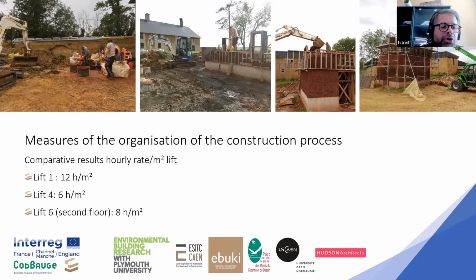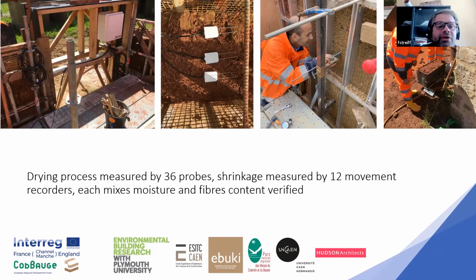And then we've seen that building a 2-story building meant that we had to use different engines on the building site, and it took us a little bit more time, 8 hours per square meter. We have measured the drying process. So the School of Engineers put lots of probes in the walls to have a good survey of the drying process.